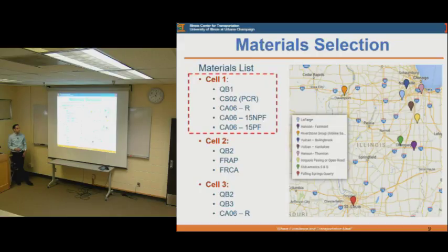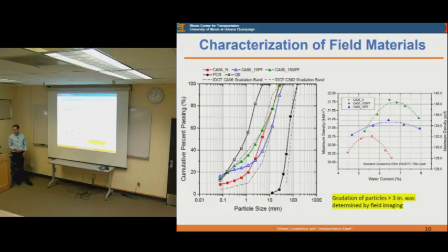CA06-R is a capping material that we used, and it has the regular percentage of fines that is currently permitted, as well as 2 materials that were engineered for this project at a higher percentage of fines: 15% non-plastic fines and 15% plastic fines with a plasticity index of 8. And those were obtained from 2 quarries in the Moline area and 1 near St. Louis. For the other cells that I will talk about later, we were blending quarry byproducts and stabilizing them. Quarry byproducts were blended with the RAP or recycled concrete aggregates, and we also obtained these from some local sources in Champaign. So we started with some characterization of the field materials.